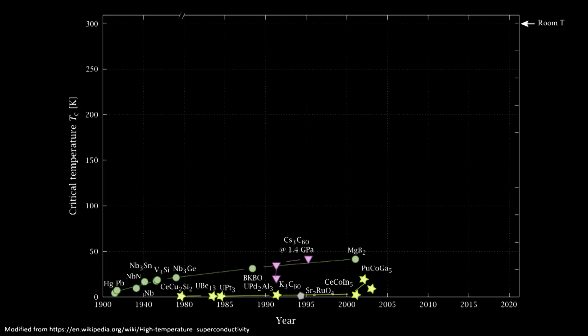I really want to motivate this graphically with a very famous plot in my field, where we plot a series of critical transition temperatures on the y-axis, which gives me a feeling for the energy scale guiding superconductivity. How strong is superconductivity in these materials as a function of the year at which that superconductor was discovered, on the x-axis. So over the many decades, we've seen many low-temperature superconductors, many of which are described by this conventional theory of superconductivity.